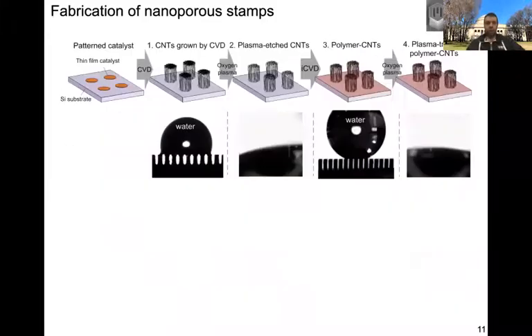And to make these stamps work, we don't just have to grow CNT forests, but we have to do some surface engineering that we figured out. And the surface engineering is required both to enable the CNTs to be wetted by the ink and also enable the CNTs to be stable when they hold the ink. So now I'll show you a couple of videos.